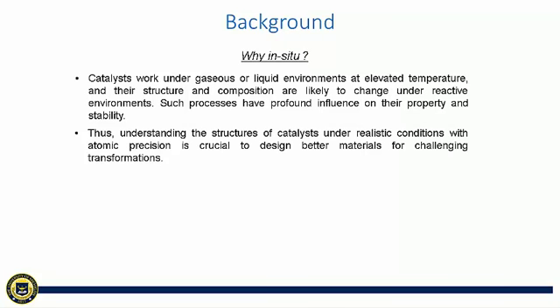As with most high-resolution techniques, it requires working under a high vacuum environment. But why do we bother to introduce gas into the microscope? The reason is that most catalysts work under gaseous or liquid environments at elevated temperature, and their structure and composition are likely to change in the reactive environment. And those changes usually have a profound influence on their property and stability.